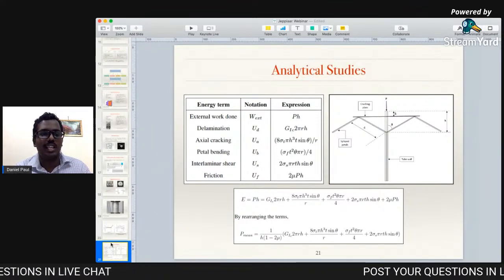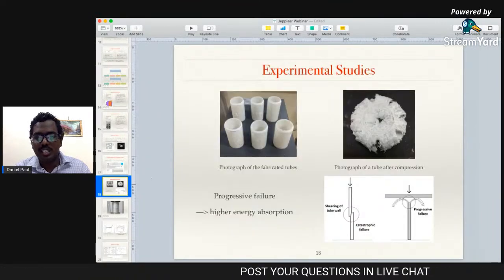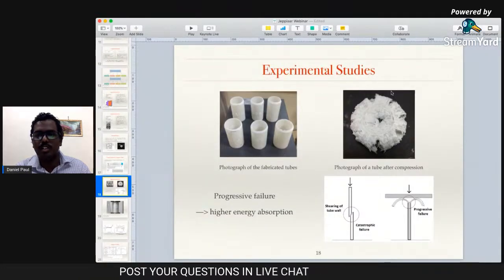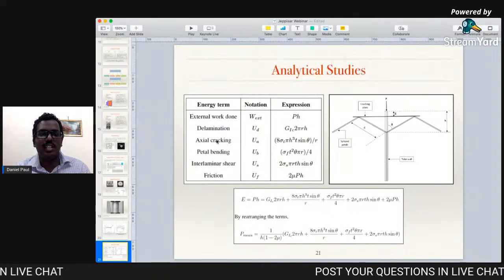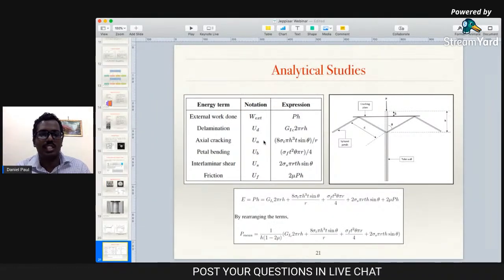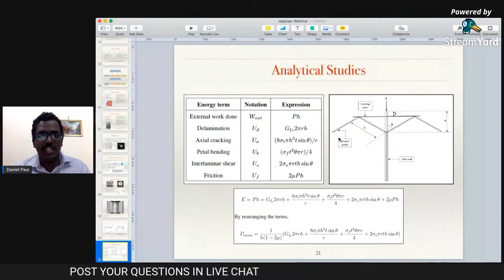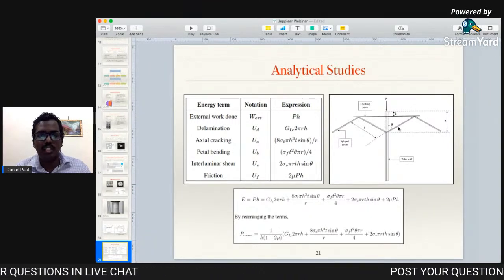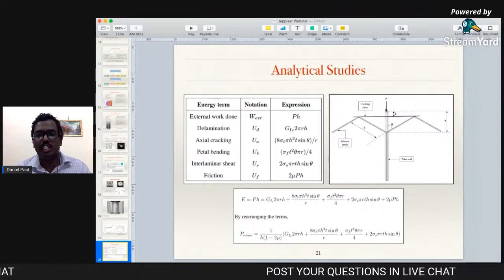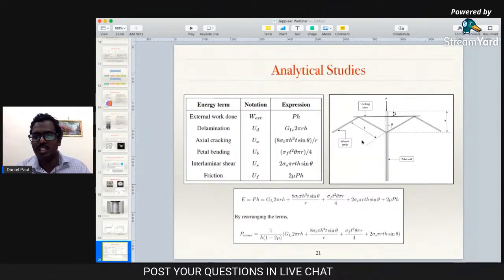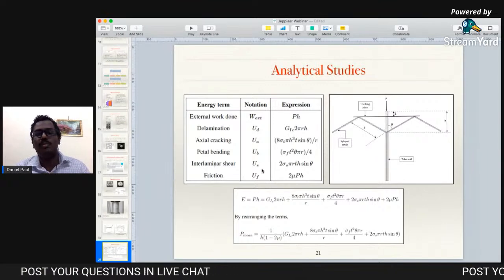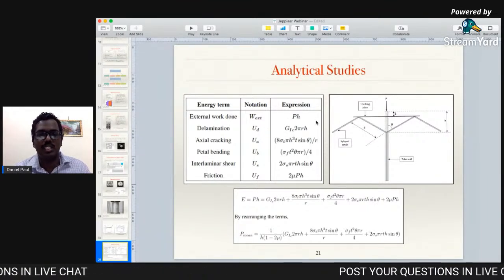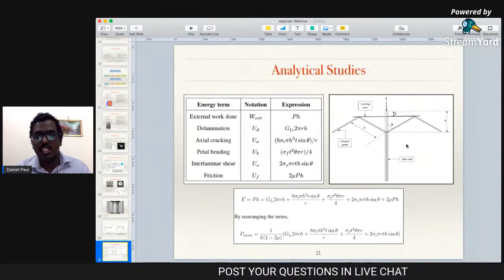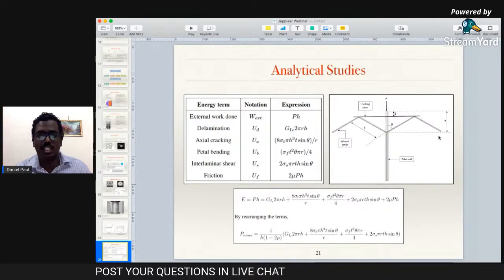Axial cracking is nothing but these axial cracks which are formed in the longitudinal direction. Because of this cracking, there is some energy that is absorbed, and due to petal bending and interlaminar shear in the petals, and also due to friction between the crushing plate and this composite, some amount of energy is absorbed for each crush cycle, for each crush length.